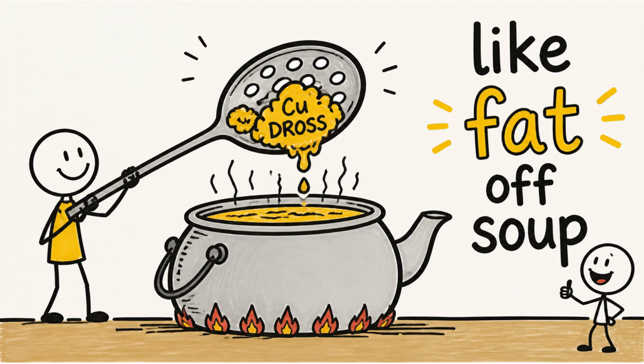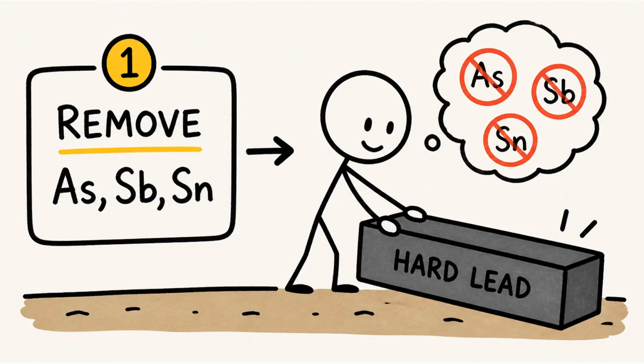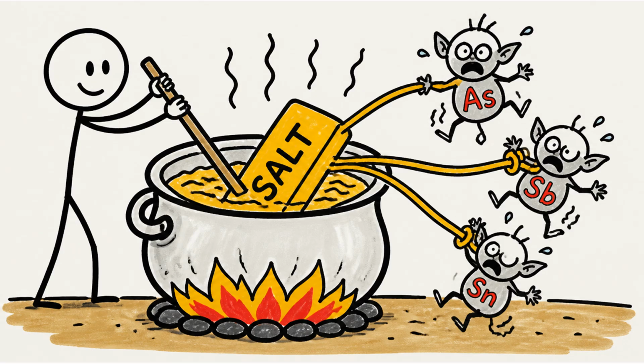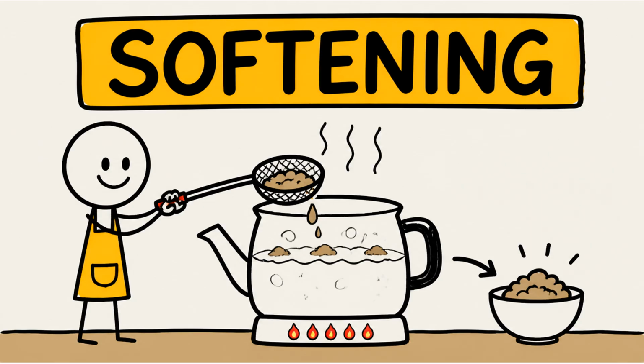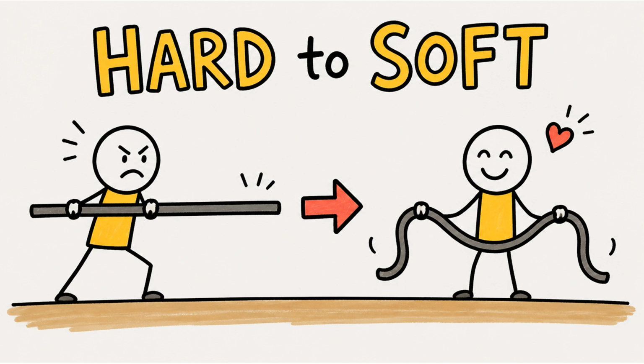They call it dross, and a worker skims it off the surface with a giant spoon, like fat off a soup. Next, the metals that make lead hard: arsenic, antimony, and tin. They stir in molten caustic salts, which grab those 3, pull them out, and float them off as more scum to be skimmed. Metallurgists actually call this step softening, because those are the very elements that make lead stiff, and taking them out makes it soft again.